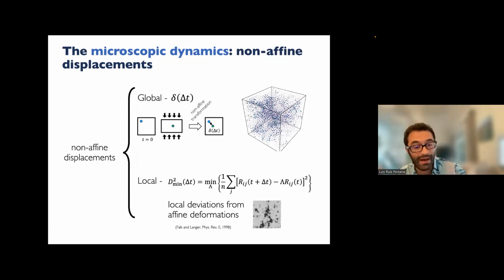We have two different measurements. One is global non-affine displacements. These are calculated with respect to the global strain of the system. And then local non-affine displacement. This is a metric that Falk and Langer came up with in '98, which is widely used in granular systems. And it measures local deviations from affine deformations. So this is a local measure, right? What you are doing basically is calculating a strain tensor around the particle and seeing how that particle has moved with respect to that affine strain tensor.